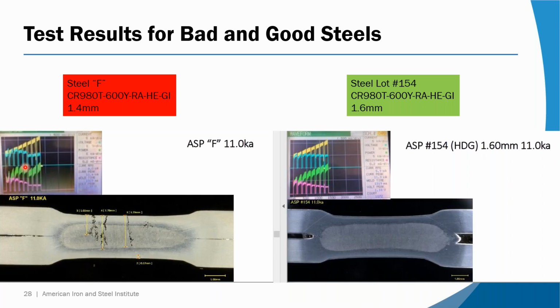Pretty interesting. So anyway, when you have a sudden drop in power between the 5th and 6th pulse, and you have that force fluctuation, which I'm not even keeping track of here, it just changed the whole crack formation mode. The crack is probably forming at this point in time, and it just didn't get a chance to make the type B crack because the type A crack preceded it and maybe relieved some of the strain, or whatever, the stress.